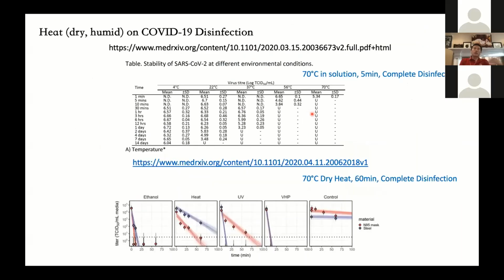Then you might want to ask the question, what temperature and treatment condition is needed to kill the COVID-19 virus? There are multiple studies now showing that in solution, 70 degrees Celsius for 5 minutes is sufficient to disinfect the SARS-CoV-2 virus completely. But the dry heat condition is different. It's not in solution. One study showed 70 degrees Celsius dry heat for 60 minutes disinfected all of the SARS-CoV-2.